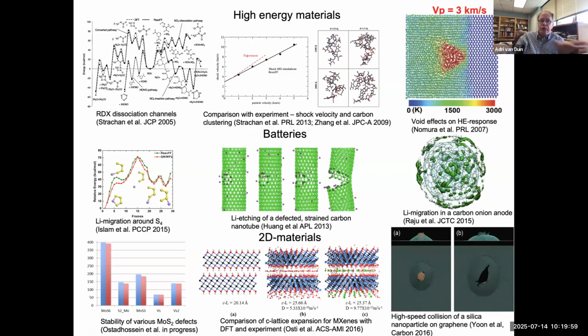A carbon anode is not just a couple of simple graphitic sheets. It's a much more complex type of environment, like for example, these carbon onions are very popular. And we can look at how lithium interacts and how lithium actually reacts and changes the carbon network during charge-discharge cycles.